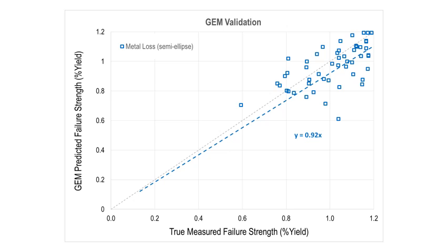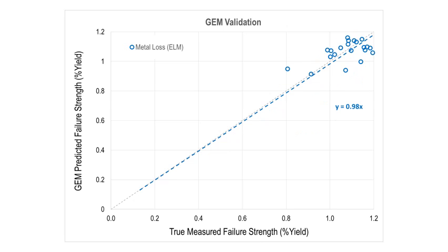But what I found is that when I use it on the 23 full profiles from the corrosion data, I find a big improvement. Here I have a trend line that goes through my data points of y equals 0.98, which means that that's about 2% overly conservative. But you've seen that the data points really tighten up.